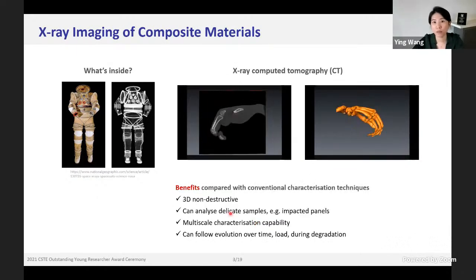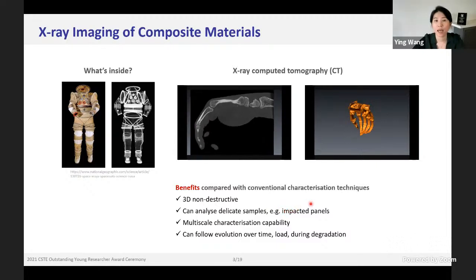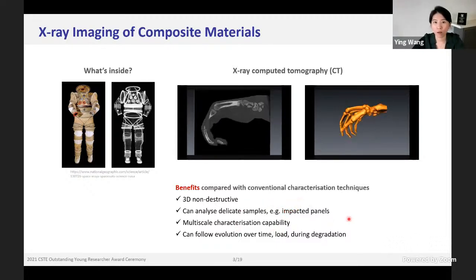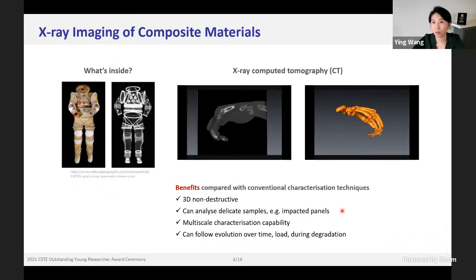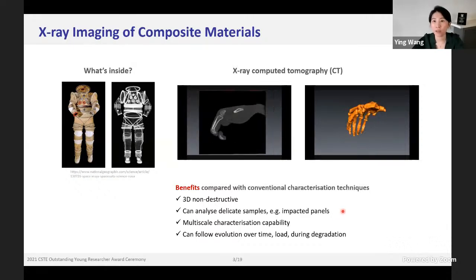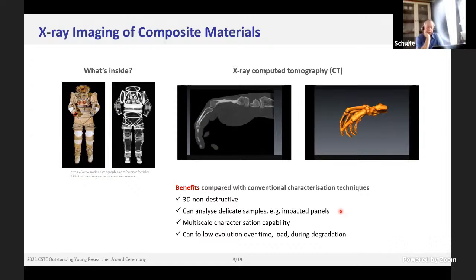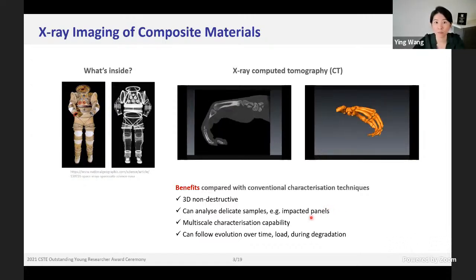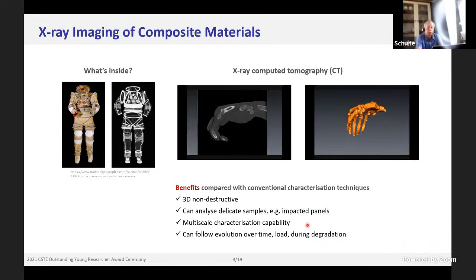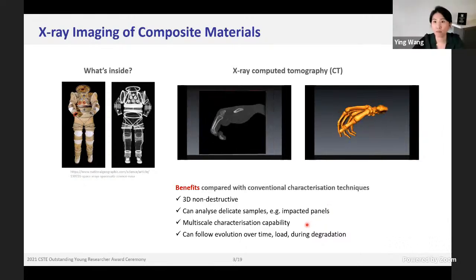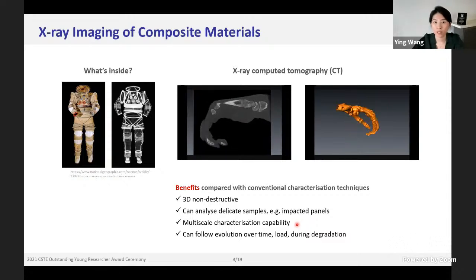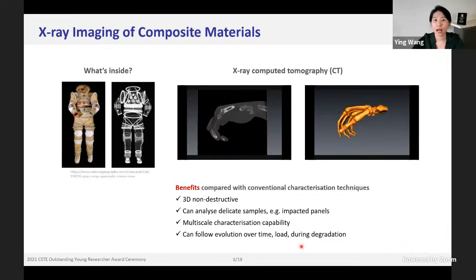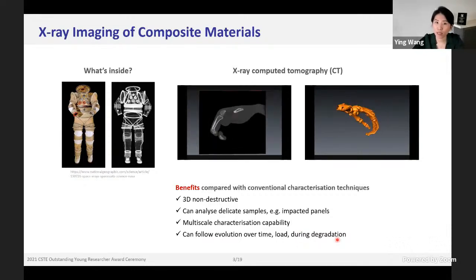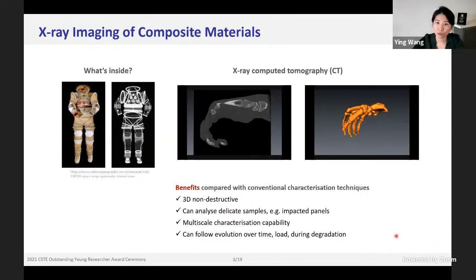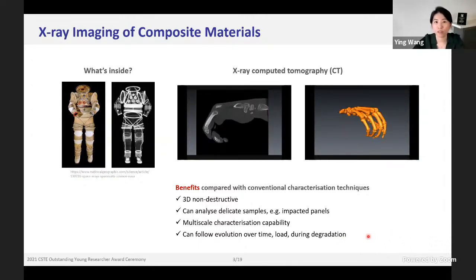So compared with two-dimensional conventional characterization techniques, X-ray imaging is really helpful for composite study since we can analyze delicate samples such as impacted composites without introducing more damage to the sample. And also, as Carl mentioned, the multi-scale characterization capability of X-ray imaging is really fantastic to understand composite materials from the fiber scale up to the component scale. And also, most importantly, we can follow the evolution over time, under load, and during degradation by using X-ray imaging.